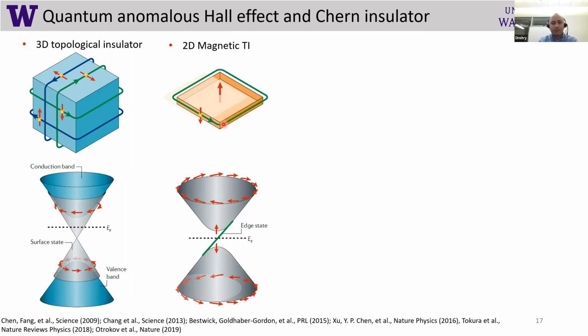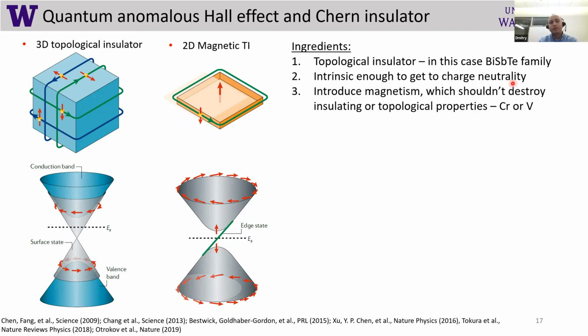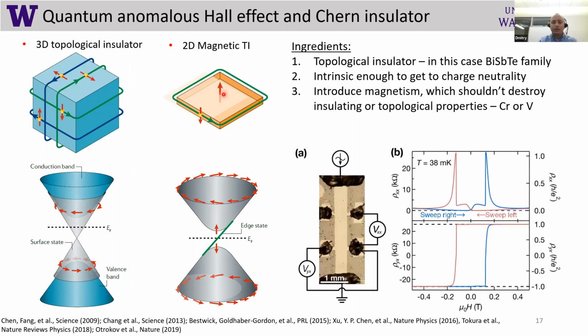I described before. So the ingredients to create this system are to take a topological insulator. The most studied system is bismuth antimony telluride. Then we need it to be intrinsic enough so that we can get to charge neutrality. For example, if we cannot get to this gap, we cannot do anything. And then our magnetism should be introduced very carefully so we don't break other aspects of the material. And this state was realized in 2013, and then many people reproduced it.